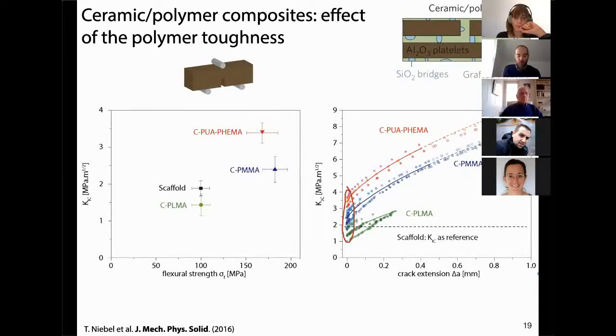And the good thing is for all these materials, we see a rising toughness, so a rising R-curve. So the crack is harder and harder to propagate as the material presents more and more reinforcing mechanisms.